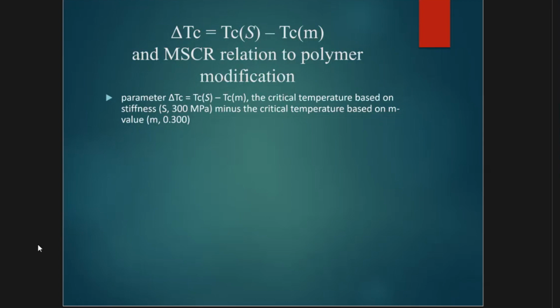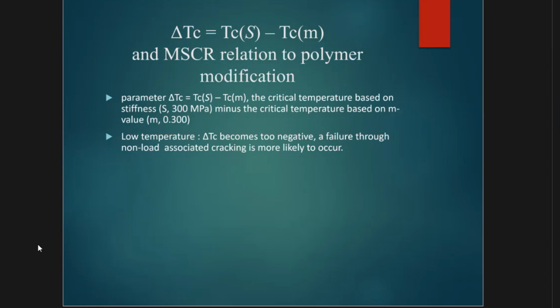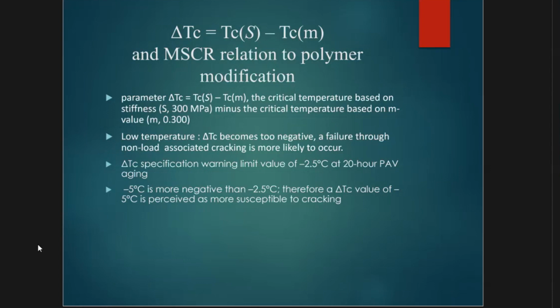So what you have is this critical temperature, and when you reach these particular numbers, you want to see what those differences are. What's the magical number? The delta Tc is actually measured in the thermal cracking of the binder, and it's a specification that could be -2.5. The best today, they agree, is not a consensus number, and it depends. Some agencies take some recommendations, and one of them today is -5 degrees C.